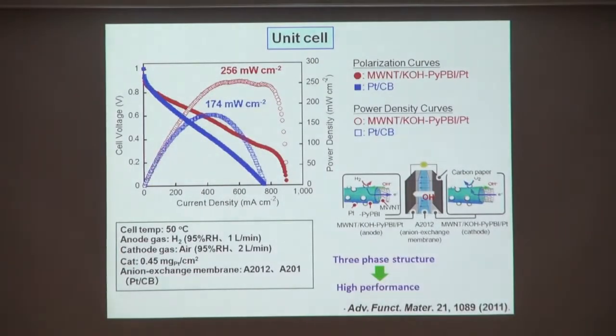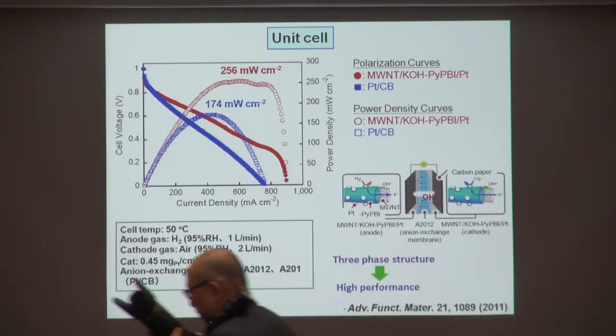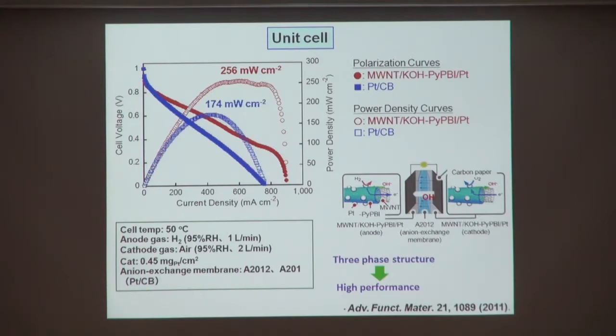Yeah, and the performance is shown here. So our alkaline type performance reached this level. Power density reached 250. That is very high in alkaline type. So we published the result about 1.5 years ago. But at the time, this was almost world top level fuel cell catalyst. And we have now improved this result, performance.